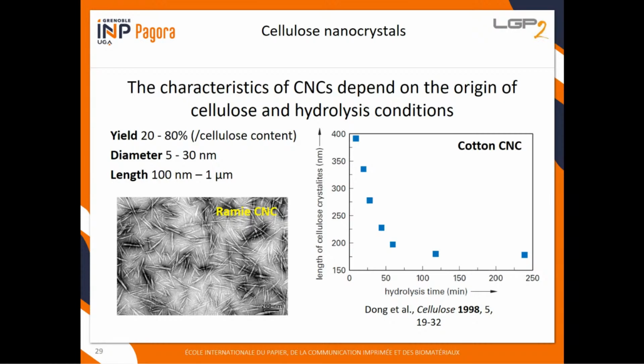You can see here the evolution of the length of these nanocrystals as a function of the duration of the hydrolysis treatment. It decreases and then levels off when all the amorphous domains have been degraded or dissolved.